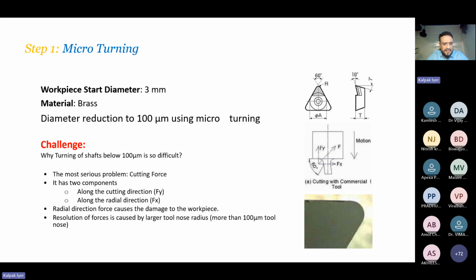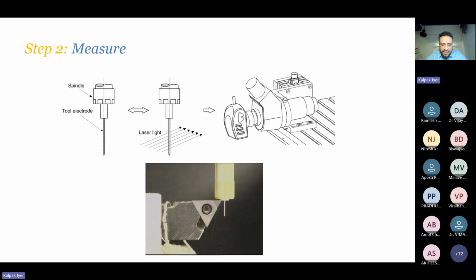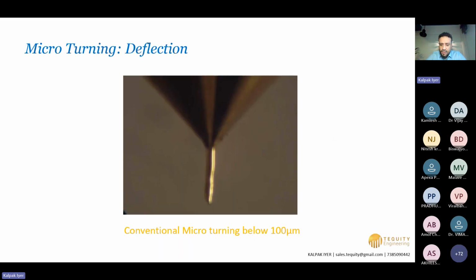Harshit sir said very aptly that up to 100 micron, micro turning worked quite well, but after 100 micron... So let me start: a brass workpiece was selected, and then micro turned up to 100 micron. No worries, the machine is so well built, it did it, and you were able to see it live, happening live. You can see the image here, and then we tried to go below, and this starts happening, deflection, and it's quite irritating, this deflecting.